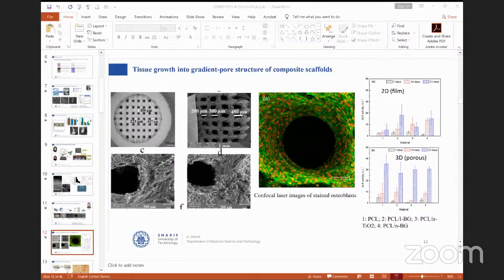especially it is very important to have a material with a porosity gradient. So, for example, if you want to join a bone to a cartilage, it's important to have a porosity gradient so different cells can penetrate and grow inside the porous structure, as you see in the SEM structure of our scaffolds. And then we have found that the tissues grow well inside the pores and make the pores very circular, as you see here, the confocal image in the middle of the slide, the confocal image of the stained osteoblast cells that stick to the surface and develop a tissue.